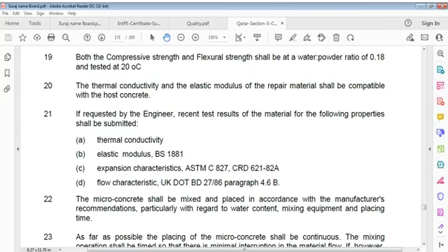Both compressive strength and flexural strength shall be at water powder ratio 0.18 and tested at 20 degrees Celsius. Thermal conductivity and elastic modulus of repair material shall be compatible with host concrete.